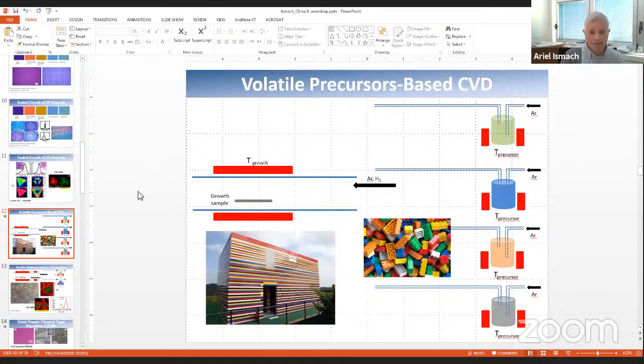Now, as I was mentioning before, the standard CVD approach used precursors that were located inside the growth system, inside the reactor. These are not the most suitable precursors to work with in chemical vapor deposition schemes. The best thing would be to have precursors located outside the reactor. So these must, of course, be volatile precursors. These are a totally different type of precursors, and if you manage to put them outside the reactor, then you can look at them as a Lego, right? So every precursor is a different color.